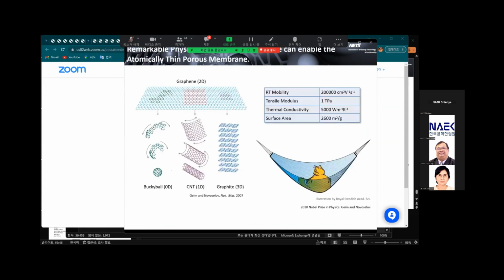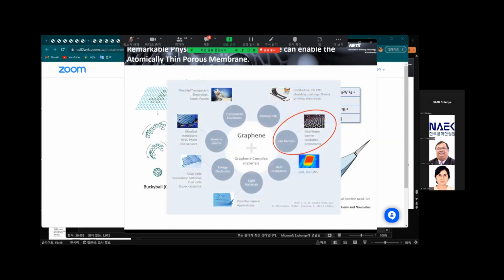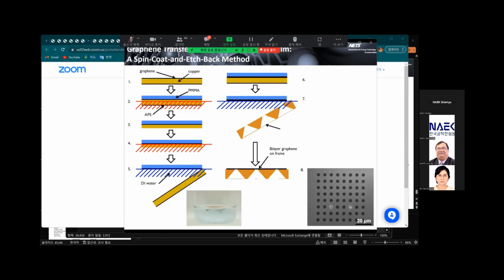Our material of choice is graphene. Thanks to its sturdy mechanical property and molecular barrier property, which implies molecular transport must take place through an artificial pore, we will perforate it on graphene. We have successfully placed 2 graphene layers on a 150 nanometer thick freestanding silicon nitride layer that has 64 of 5 micrometer wide holes.